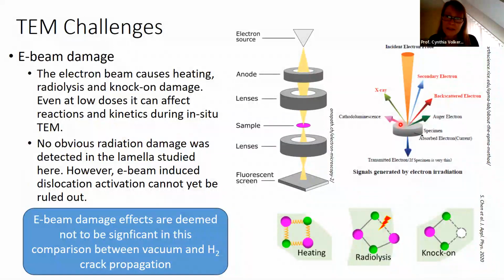The ones we're most concerned about, the changes in the material that are most significant, are listed down here below. We create local heating. The excitations generated primarily in the electrons of the material then relax and thermalize, and we end up with local heating in the material. We can break bonds through the interaction of the primary or other electrons with electrons in the material. We can end up with what's known as radiolysis and break bonds, which of course changes the material. We can even in some cases end up with direct knock-on of atoms, where we are able to knock atoms out of their lattice sites or their positions in the specimen. So these are things that an electron beam can do.